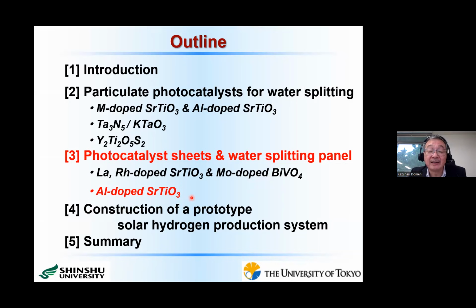Okay, now let me move to another example of the photocatalyst sheet. In this case, we use aluminum-doped strontium titanate. This aluminum-doped strontium titanate is exactly the same as this aluminum-doped strontium titanate. However, in this case, we needed to prepare a kilogram order of aluminum-doped strontium titanate photocatalyst. So in this case, we deposited our co-catalyst by the so-called co-impregnation method. It is not as sophisticated as I explained previously. The apparent quantum yield of the water splitting reaction in this case was about 50 to 60%.